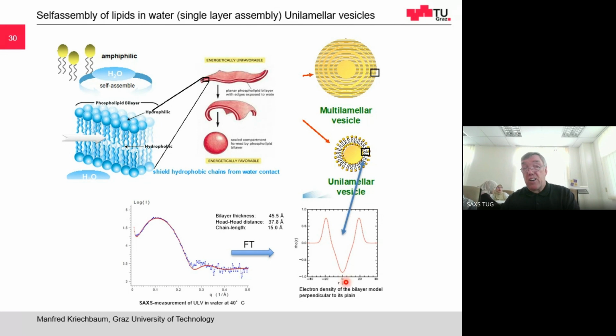So in the interior of the bilayer, you have a low electron density, and on the outer surface, which is exposing itself to water, you have a high electron density. So this way, you can also study, if we insert some tracer, if it is in the bilayer or if it is in the inside of this unilamellar vesicle. So where the tracer is located, you can determine the location of your tracer.